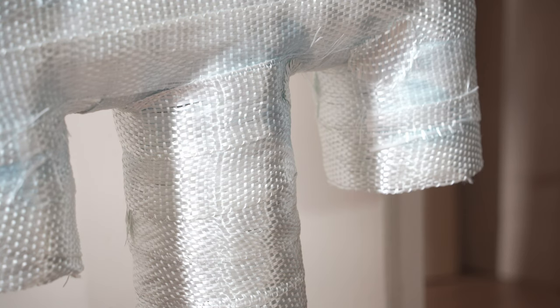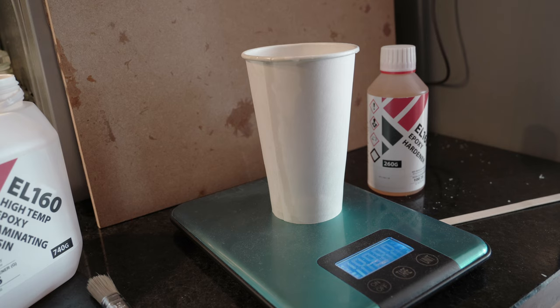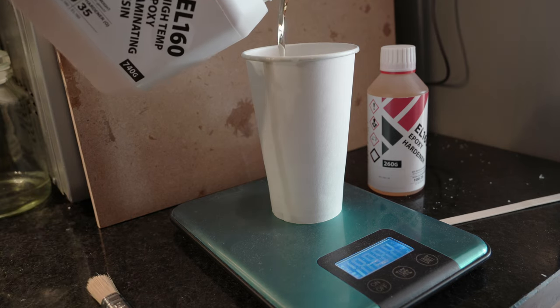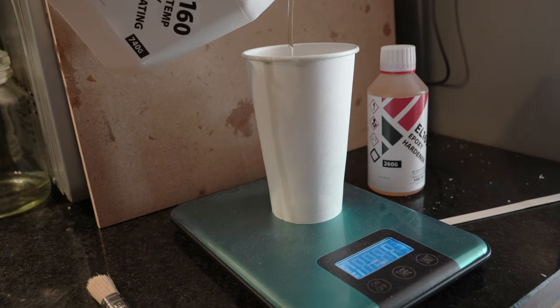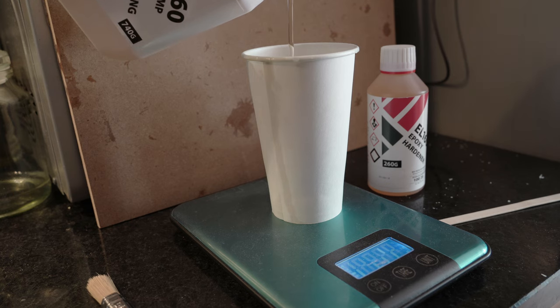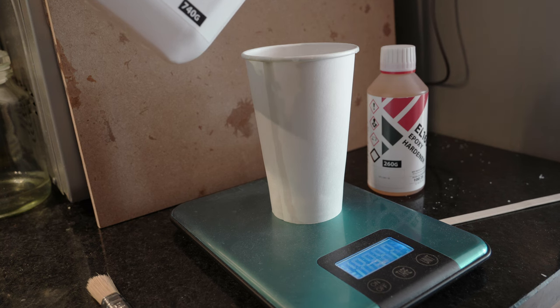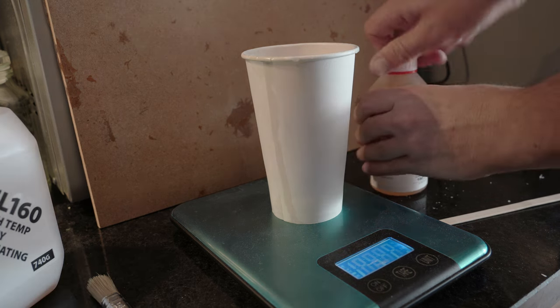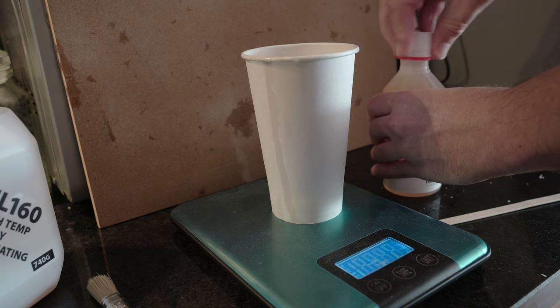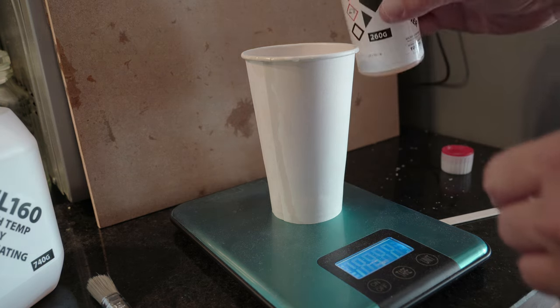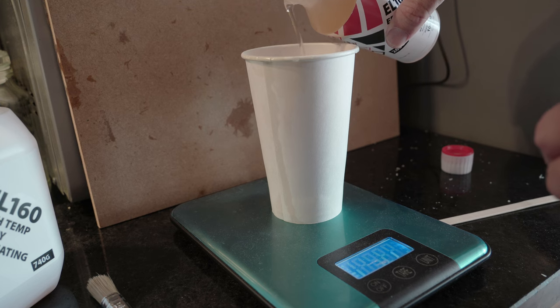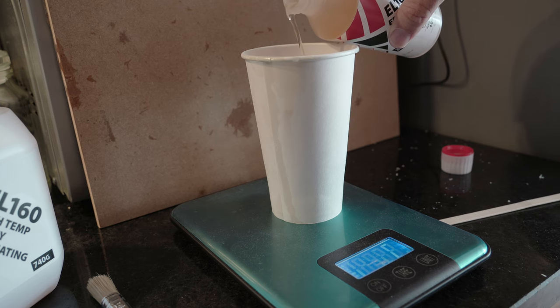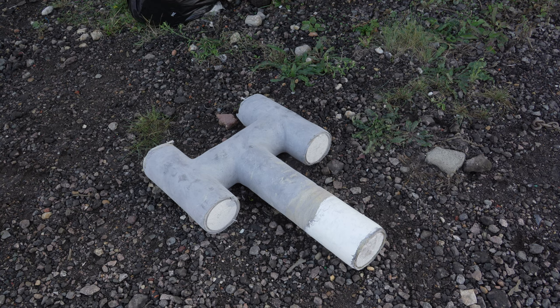Of course, when I dissolve the polystyrene core later on, in its current state the hood will have no structural strength at all, so I need to laminate the outer layers of glass fibre with epoxy resin. Especially in the lower section, just in case hot air from the stove heats up the steel lining to the extent that the whole structure warms, I'm using a high-temperature formulated epoxy resin. It's not rated as high as the silicone sealant, but it's pretty good for the outer layer, at 170 degrees Celsius.